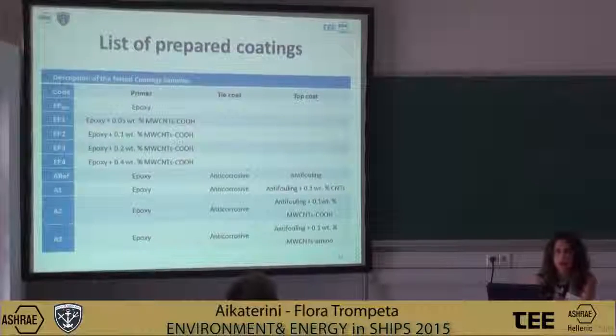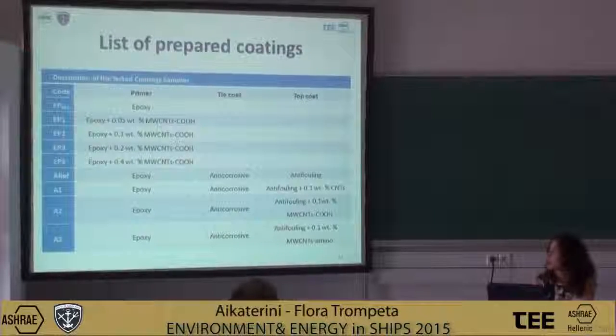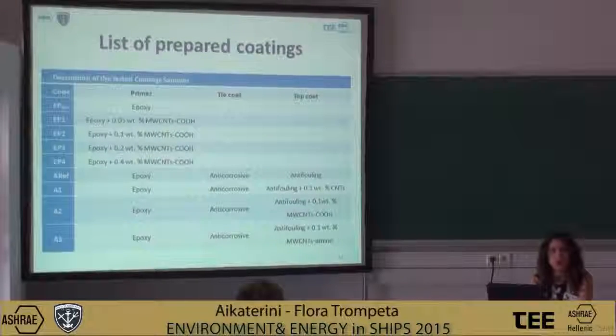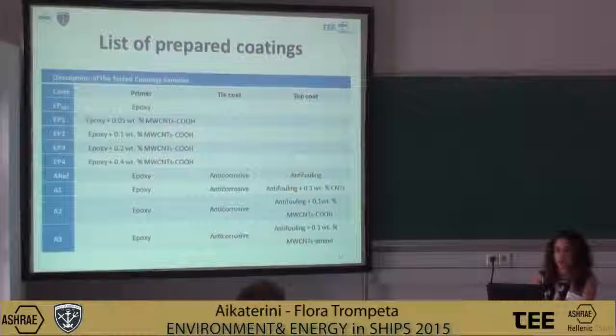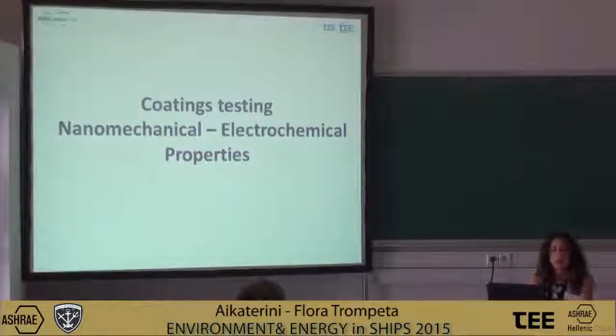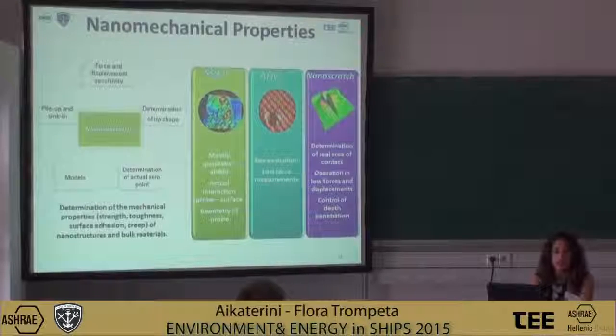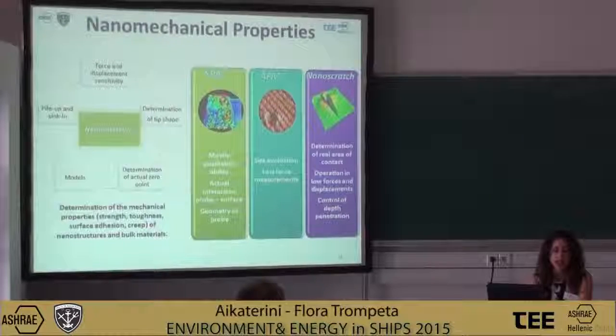All the samples that were produced are included in this table. We had two reference materials, just one epoxy primer, and another reference system with epoxy, anti-corrosive, and anti-fouling paint. We produced 4 different samples of epoxy with different concentrations of the carboxylated multi-wall CNTs, and 3 different anti-fouling coatings with the same concentration of CNTs, but using CNTs with different functionalizations. After the preparation of the samples, the nanomechanical and electrochemical properties were tested. For the nanomechanical properties, we used a nanoindenter.